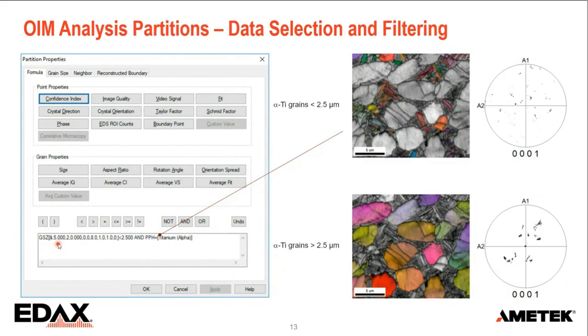In this case, a tolerance angle of 5 degrees, which is the default in the system. And then grains have to be smaller than 2.5 micron. And the phase has to be, in this case, alpha titanium. So when I have a filter like that in my partition, that's the only part of the data set that I'm going to use. So then I can make a map, I can make a pole figure, I can make a grain size chart only using those points.